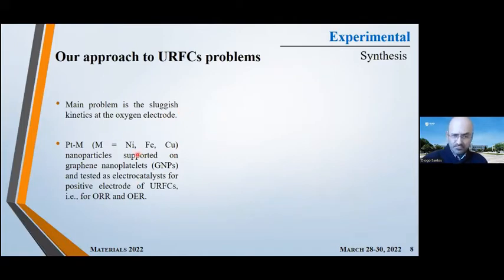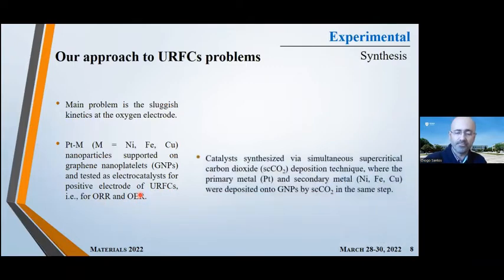So what we did here was to prepare a new electrocatalyst that is based on platinum alloyed with 3 different types of transition metals, with nickel or with iron or with copper. And these nanoparticles are supported on graphene nanoplatelets. So we have prepared these materials and then tested them as electrocatalysts for the positive electrode of these unitized regenerative fuel cells. That means for oxygen reduction and for oxygen evolution.